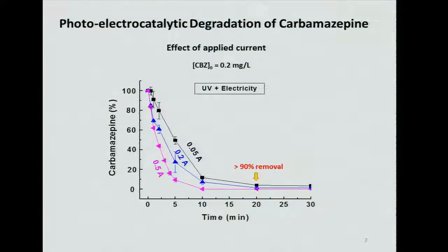We chose a pharmaceutical, carbamazepine, to test the effectiveness of our selected coating composition for the removal of a drug. Carbamazepine is a widely used anti-epileptic drug and is persistent to conventional wastewater treatment methods and even some other advanced treatment methods. Here are the results for degradation of carbamazepine using both UV and electricity. As expected, by increasing the applied current, we obtained higher degradation of carbamazepine. However, for all applied currents, above 90% removal was obtained after about 20 minutes.